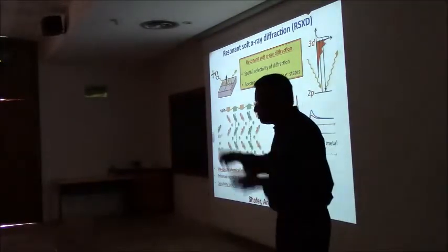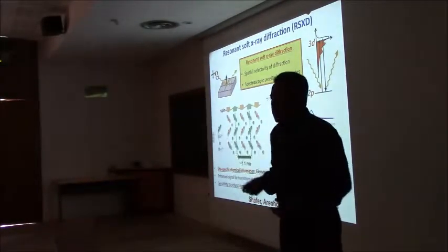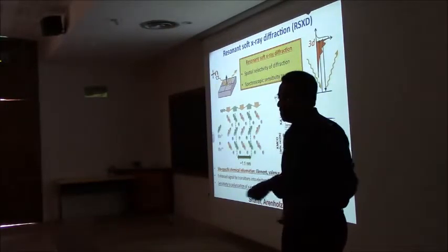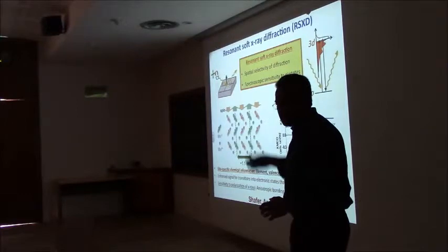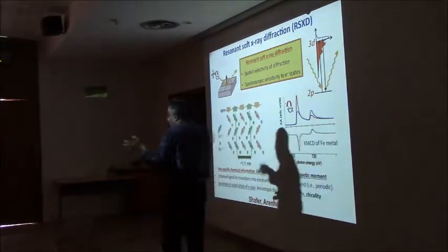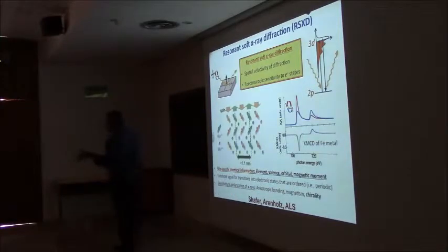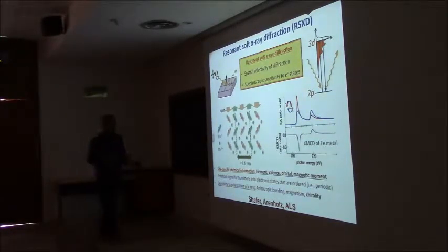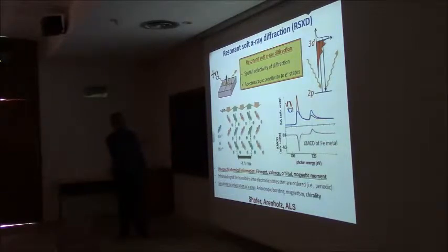The soft X-rays have wavelengths typically a few nanometers, unlike copper K alpha, which is 1.54 angstroms. This is maybe 30 angstroms. At the light source at Berkeley, we're very well set because that's typically the wavelength scale we use. So I come in with the X-ray beam, and I do diffraction.